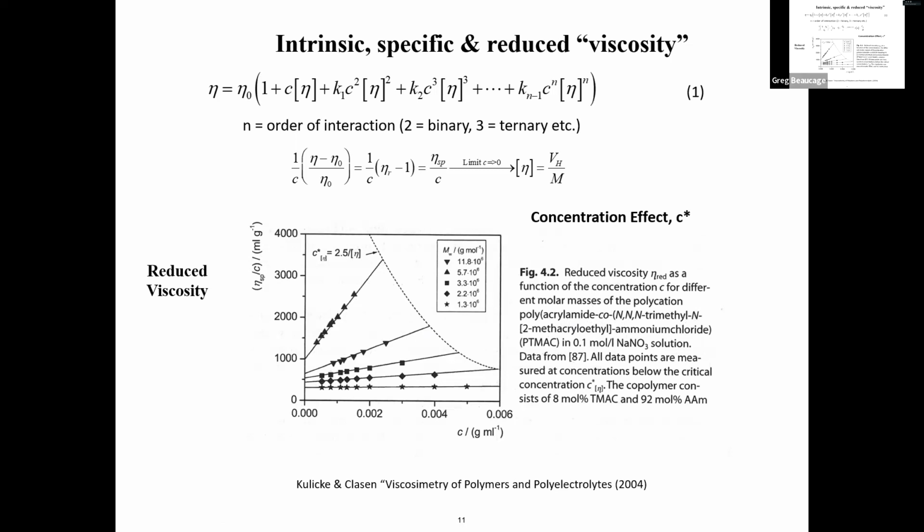Then as you increase the concentration further, that attraction and repulsion disappears because you're screening the charge with Debye screening, and they become normal polymers. So the actual beast you're looking at depends on what concentration it's at, because the charges are screened. It goes from something like a rod down to something like a coil as you change the concentration. So anyway, things happen.